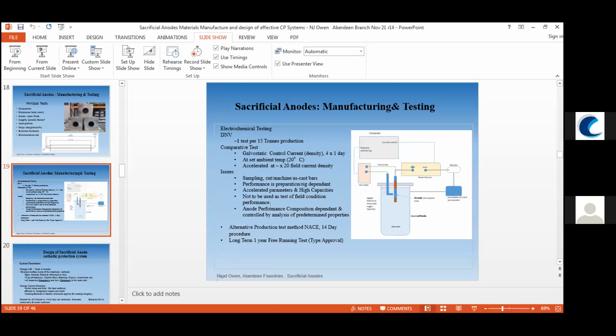Largely, I don't think it's just my opinion, but a lot is made of electrochemical testing, but it was essential when you're developing these alloys in the laboratory. Once these compositional levels were checked and field trials were done, we really are just relying upon composition analysis as being the primary way that we determine that we've made the right thing. You're more likely to get a failure from the preparation of these samples, or the test rig continuity or something, than you are a failure due to the materials themselves.